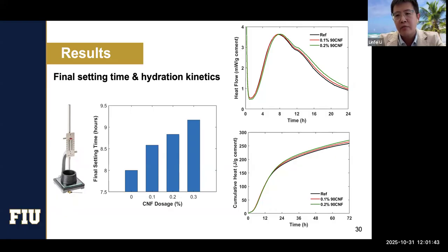So it's kind of like a block or a barrier to stop the water from directly contacting the cement. So that's another theory. People are saying we're not very clear if adding nanomaterials will accelerate or delay the hydration. But at this moment, based on what we found, without any ultrasonic dispersion, we saw a delay in the hydration process. But surprisingly, on the other side, if you see the cumulative heat, in the later stage it goes up. It's higher than the reference sample.